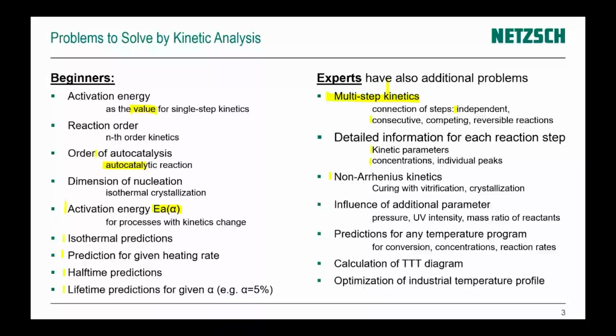Sometimes you can find that the kinetics is totally not Arrhenius, as was assumed at the beginning. For example, if we speak about curing with vitrification, then we can find that there is a glass transition, and the glass transition will change our curing mechanism. And this glass transition is not a constant value, but it changes during the reaction progress. And we must find where the vitrification is and how the reaction mechanism will change.